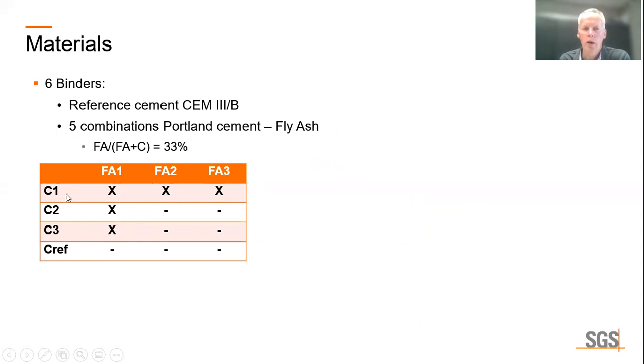By combining Portland cement C1 with the 3 different fly ash qualities, we can investigate the influence of the fly ash origin. And by combining fly ash 1 with the 3 different Portland cement qualities, we can investigate the influence of the Portland cement quality.